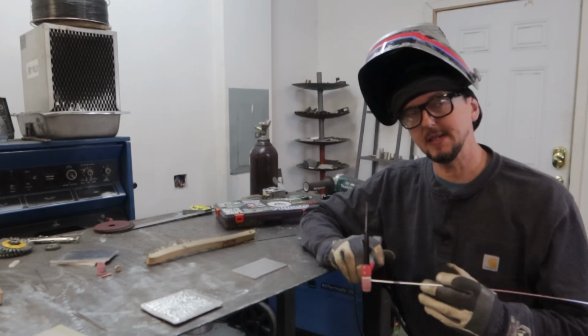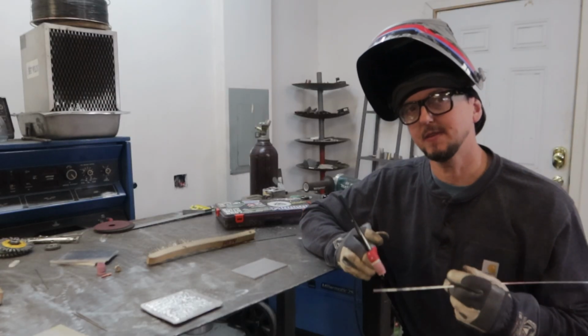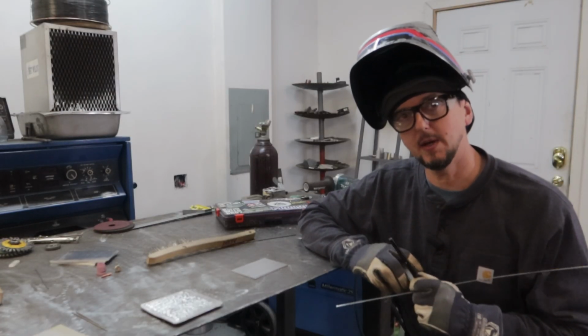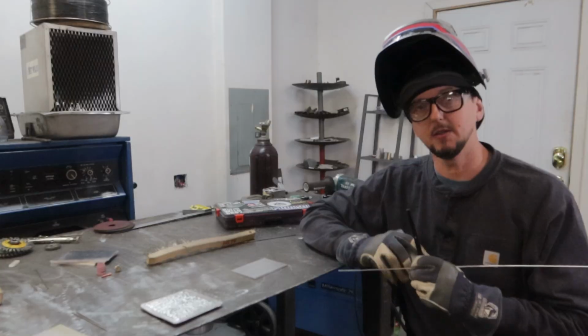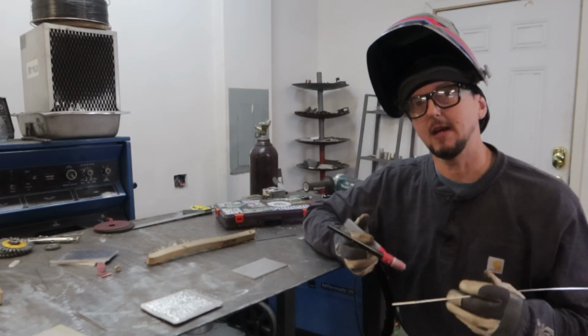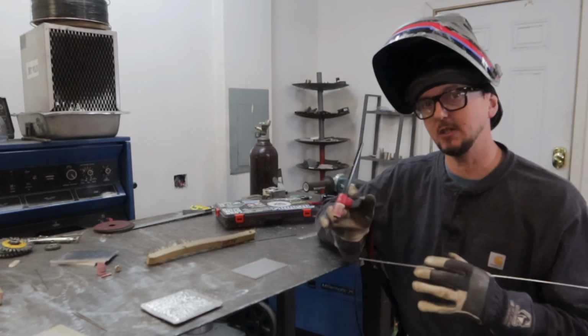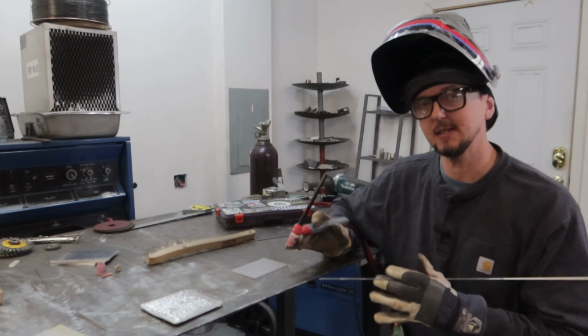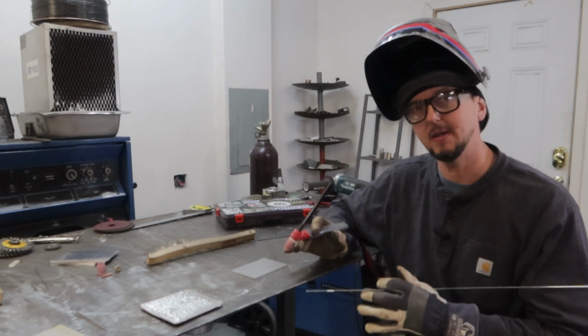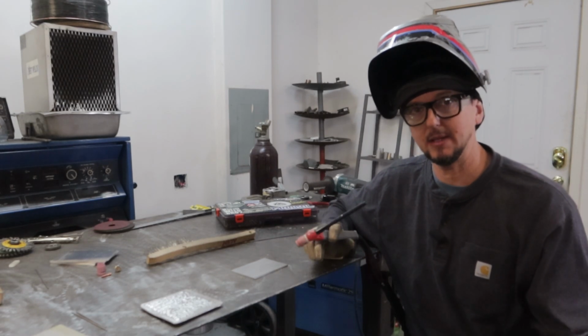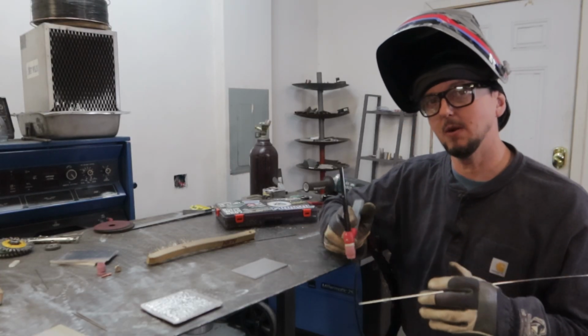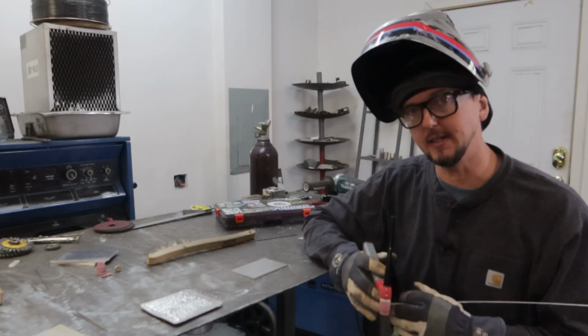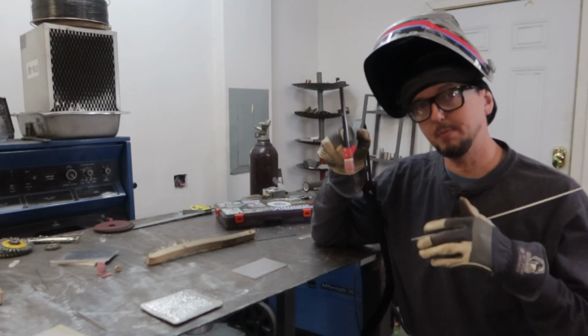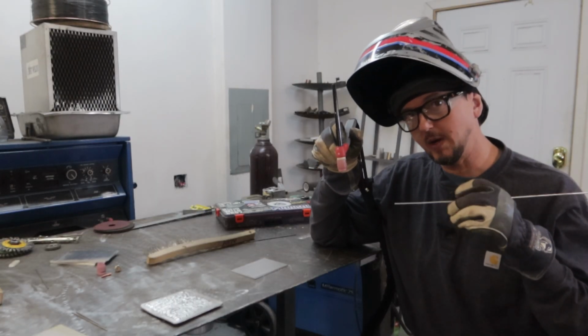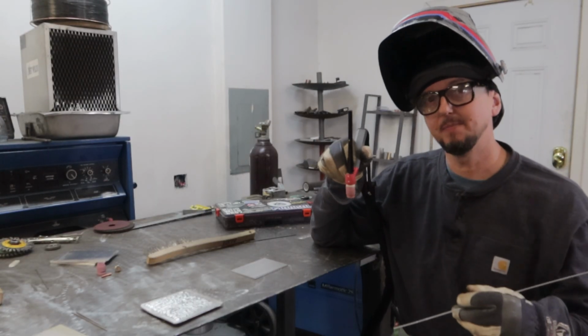down. All right, so we're going to put our first bead down on this plate, but the thing that I wanted to talk about first is just what I see with a lot of new welders when they're first starting out on aluminum. Keep in mind, we have high thermal conductivity, so especially when we're on a cold piece of plate like this, where we haven't put any welds down, we don't have any heat in that plate yet. So it's going to take a moment for us to get that weld pool started. So we need to wait for that weld pool to get nice and hot before we start adding our filler metal.